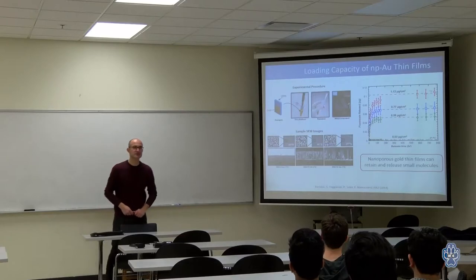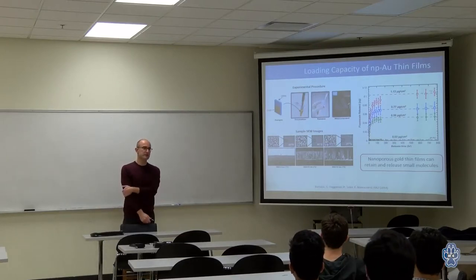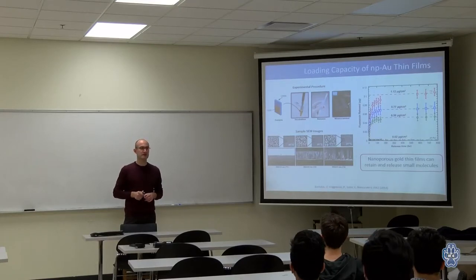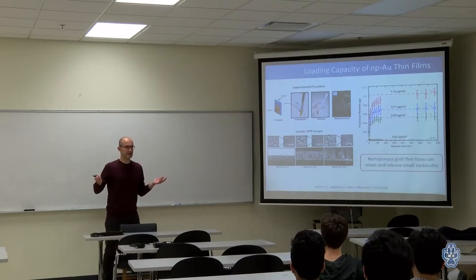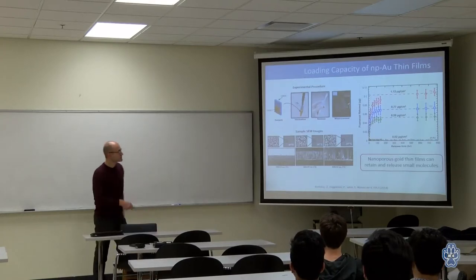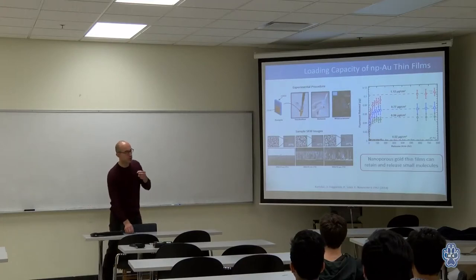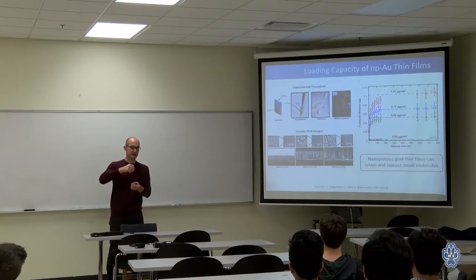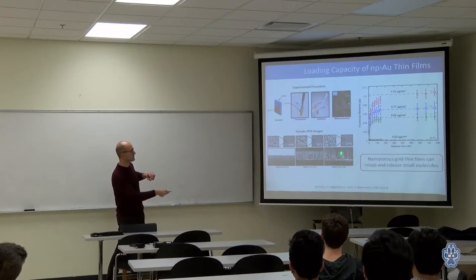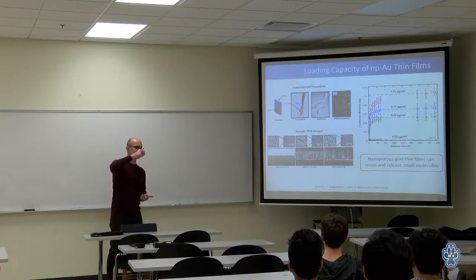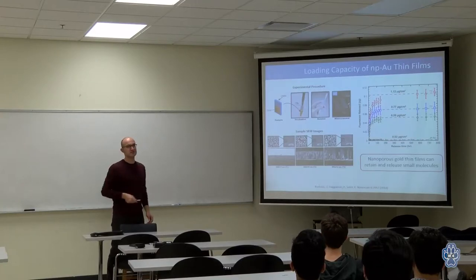Something interesting happens when you go to small scale: physics begins to change in some ways. For electrical engineering, probably like tunneling, for example, if you've taken device physics, it does not exist at macro scale, but it actually exists at nanoscale. So with really small pores, typically if you have a sponge and put fluorescent molecules in it, these are really short distances for a molecule to travel. It would take milliseconds for that molecule to come out. But here we are seeing that it's actually taking on the order of almost a day to come out.